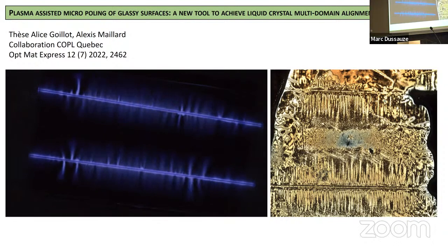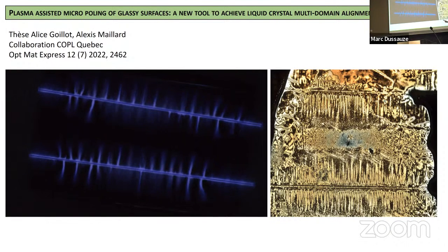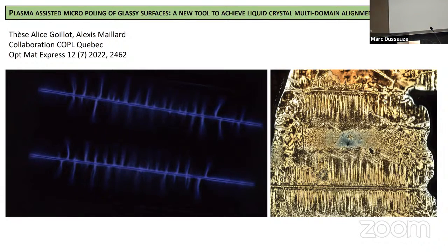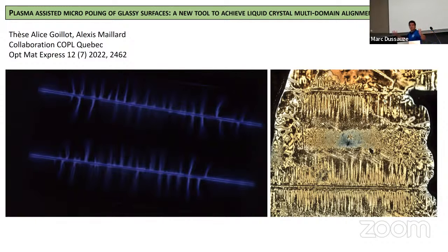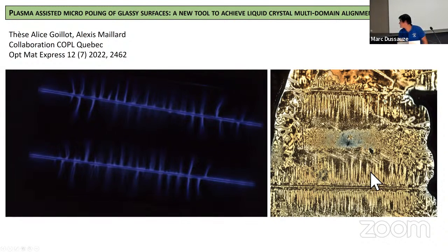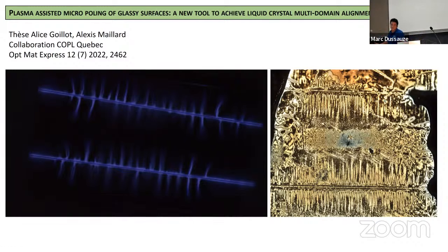We can see all the plasma discharge here, going from the string in all directions. This treatment is not at all controlled. The plasma goes in all directions. But we made the liquid crystal cell after. On the liquid crystal cells that you can see here, if you look around the string, the liquid crystals follow exactly all the plasma discharge that was uncontrollably induced during the treatment. So that's, for me, a very nice proof that it's very effective.